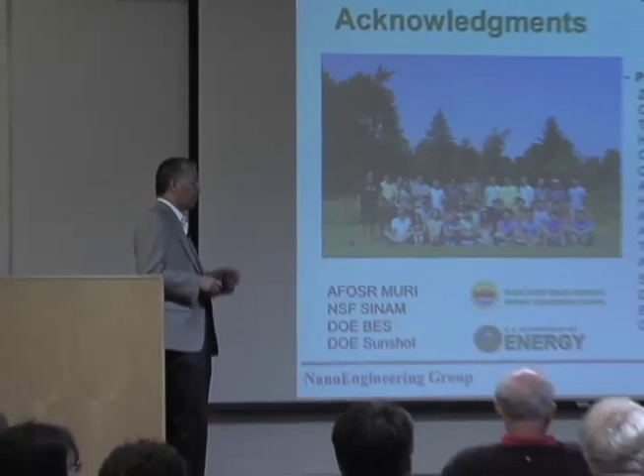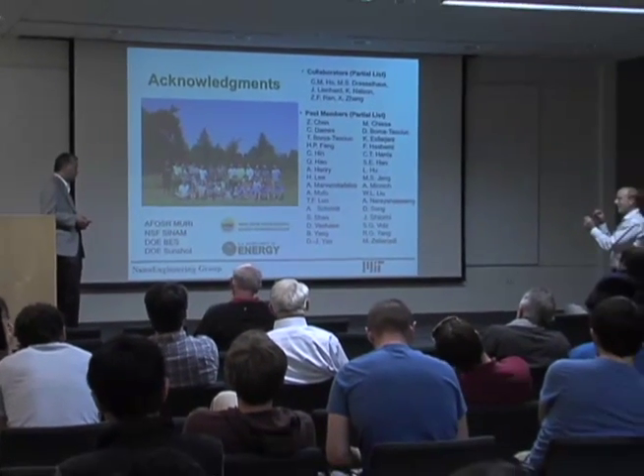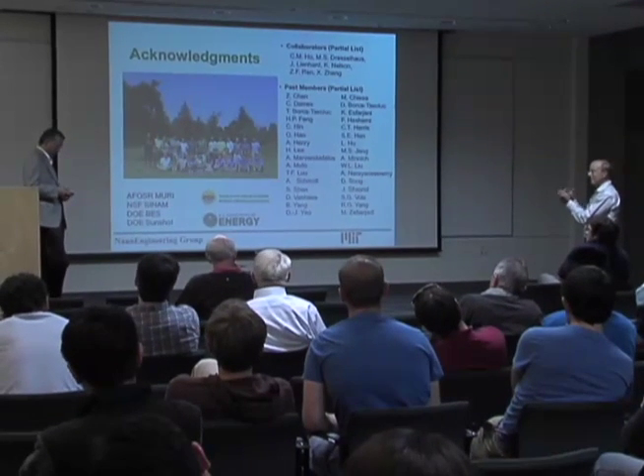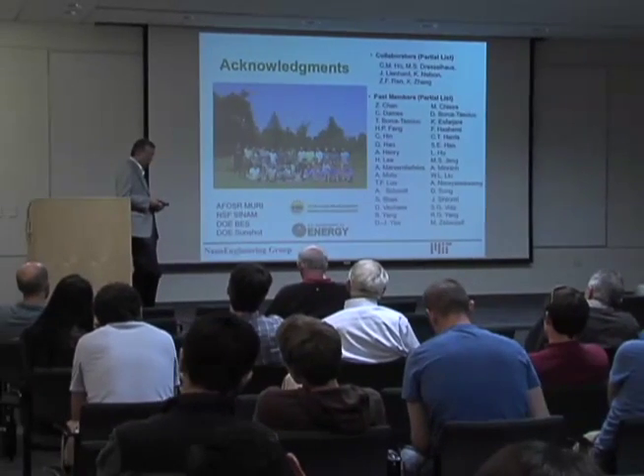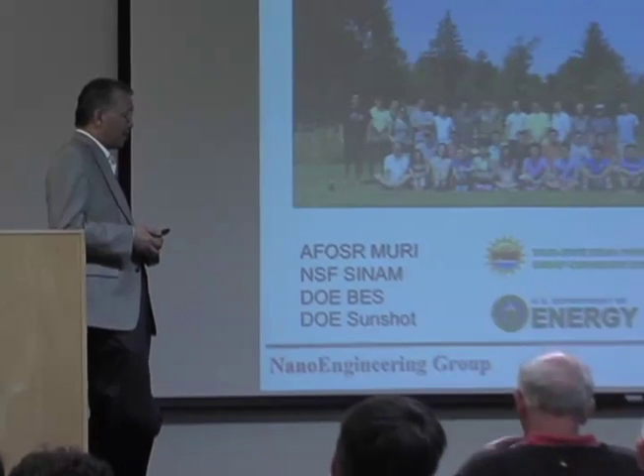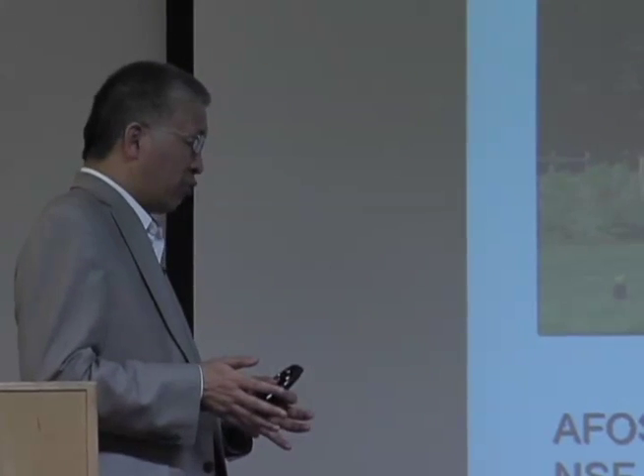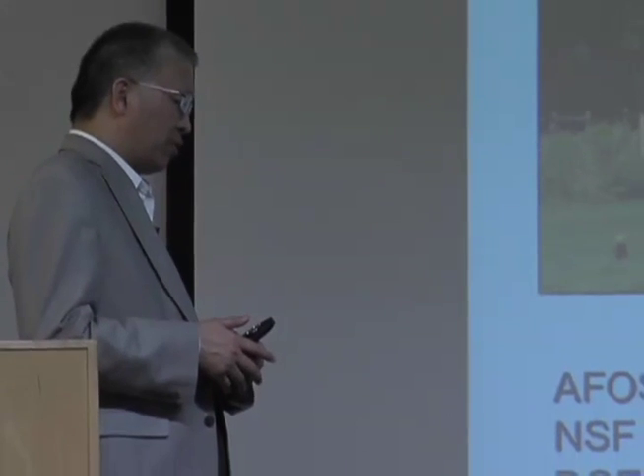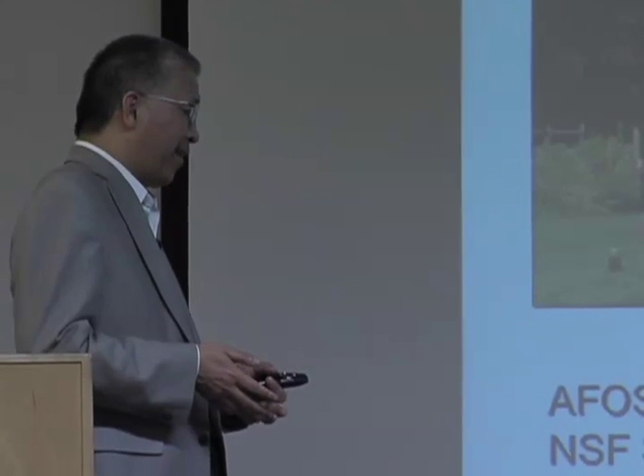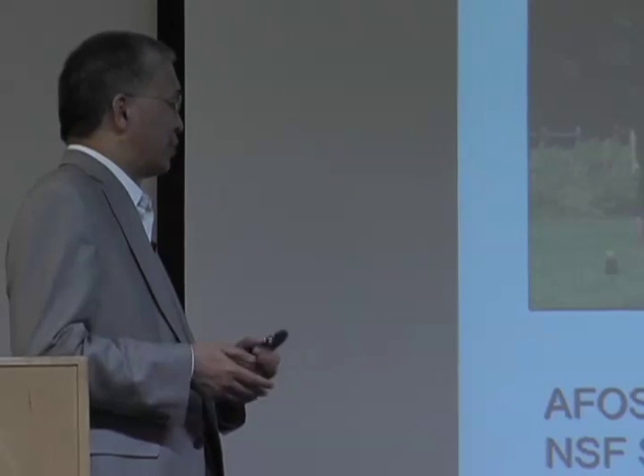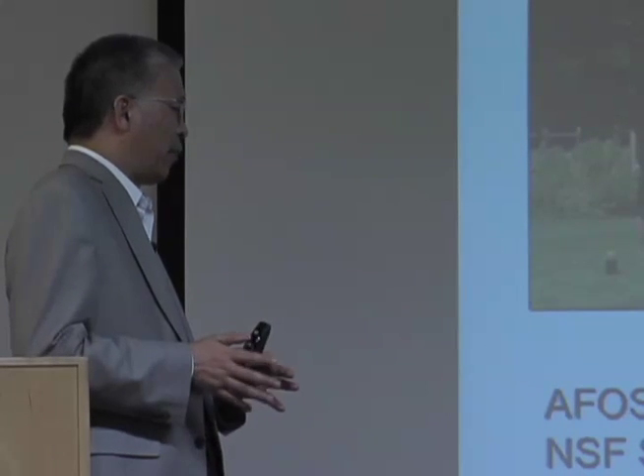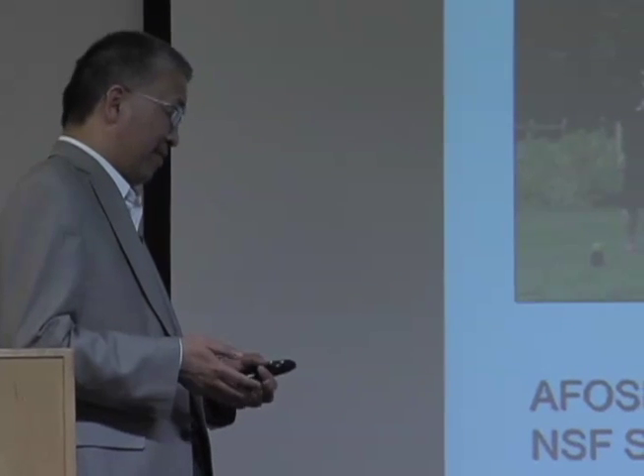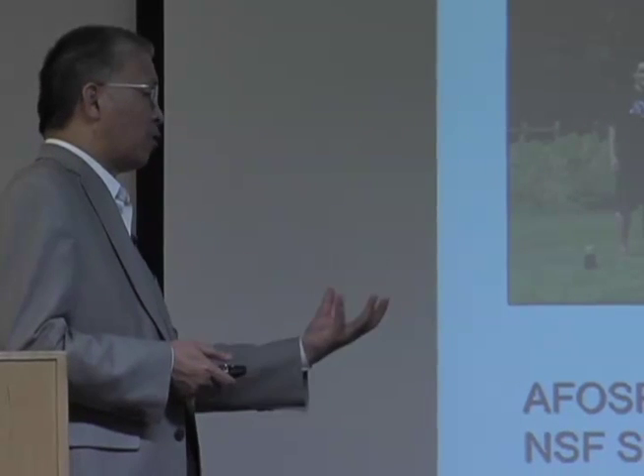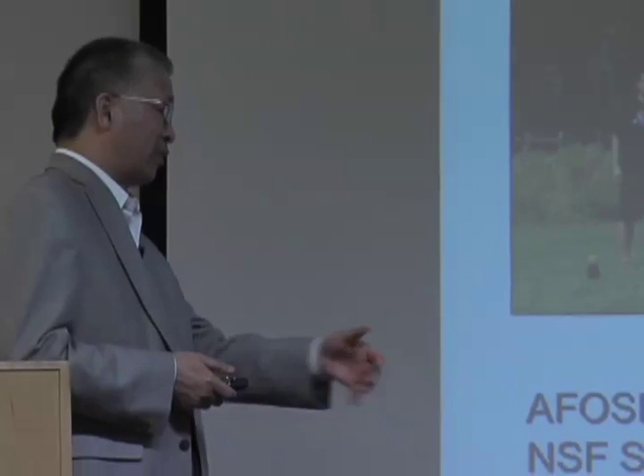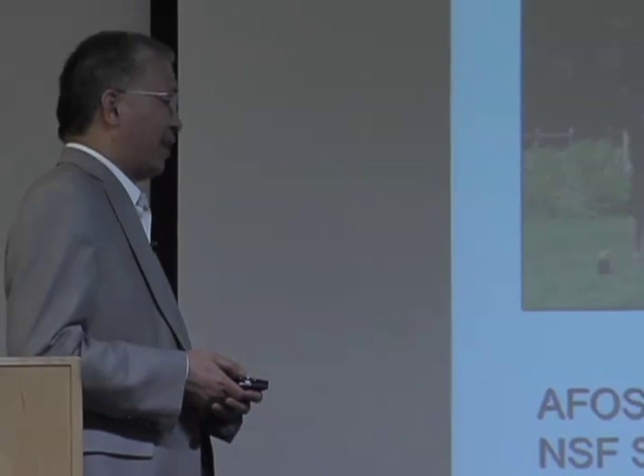Yeah. So in terms of using this for heat power generation, I guess I was assuming you have this broadband absorber, and then you transfer across to this narrow energy band. Right. And then it has to be a band-to-band detector at the other end. Right. So this is where I looked into a lot of different materials. What would be the material that has the right wavelength? Because 8 micron is just too long, and some of those materials, for example boron nitride, is about 5 micron, and the question is whether there are materials in the 4 micron range or 3 micron. That probably will go to some hydrides because of hydrogen bonds, hydrogen being a smaller atom. Basically, you want high frequency atomic vibration to gear towards the band gap. I have not found the ideal material for that.